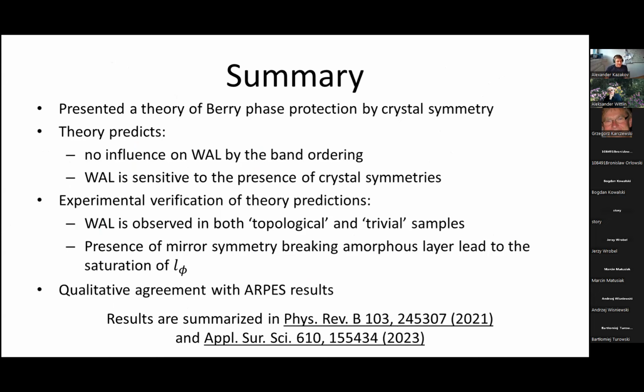We discussed how different symmetries affect Berry phase quantization, and particularly that crystal symmetry can be responsible for the Berry phase quantization. So from theory considerations, we conclude that weak antilocalization is not influenced by the band ordering, so it exists in both inverted and trivial regimes. We also calculated that weak antilocalization should be sensitive to the presence of crystal symmetries.